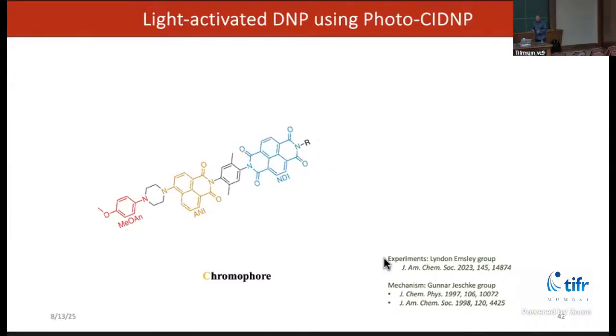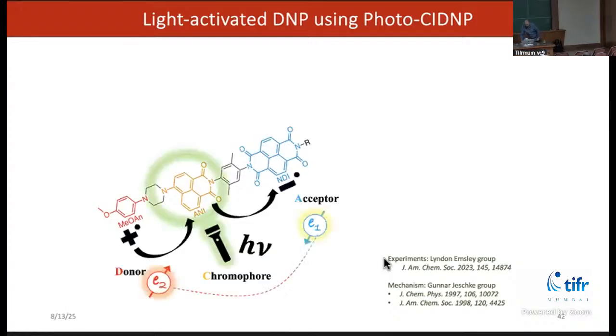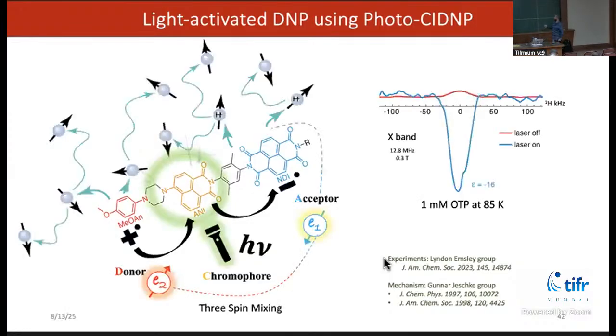So there is diamond, and there are these triplet molecules coupled with radicals. The other system which has become very exciting recently is the radical pair system, a molecular system which can generate a spin-correlated radical pair. One of the recent examples is from Lyndon Emsley's lab at EPFL. He showed that a molecule like this, which has a chromophore and a donor and acceptor of electron, when we shine light, just by shining light, it's possible to hyperpolarize the NMR signal.